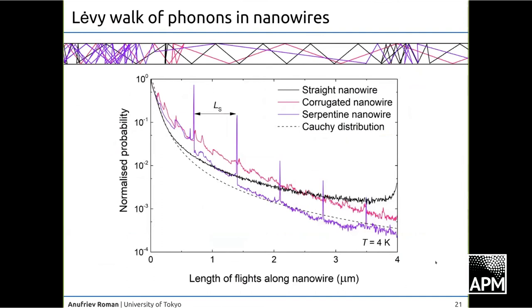The final point that I want to make is another simulation that we did. It's a Monte Carlo simulation again, based on a particle view of the phonon. We represent each phonon as just a line, and there are all the necessary rules of scattering and everything, but the take-home message here is that it seems like heat conduction, let's say phonon transport in nanowires, can be seen as a Levy walk rather than a random walk, with bursts of diffuse scattering between the walls.